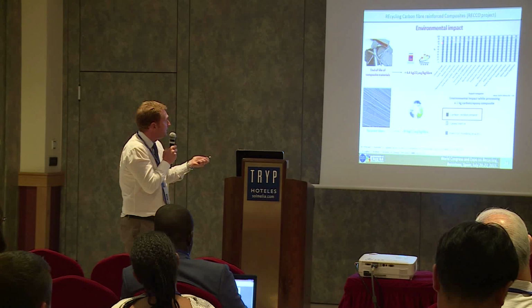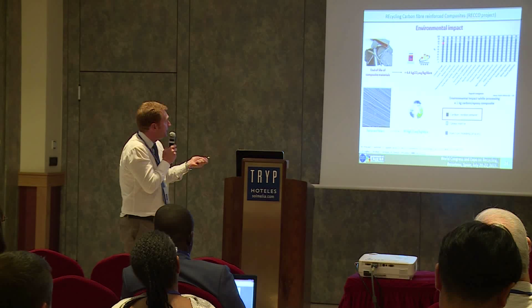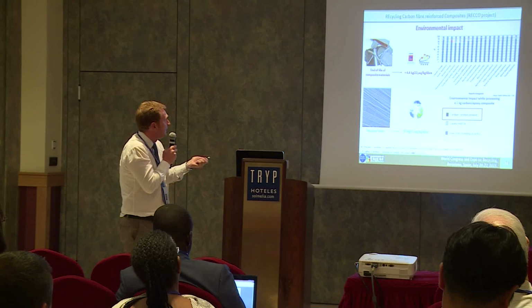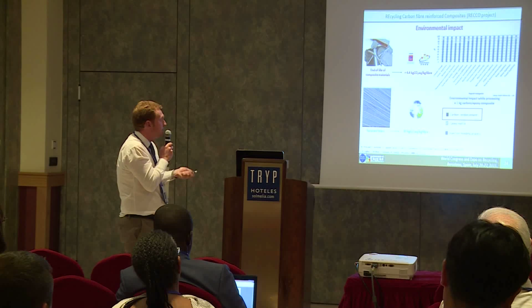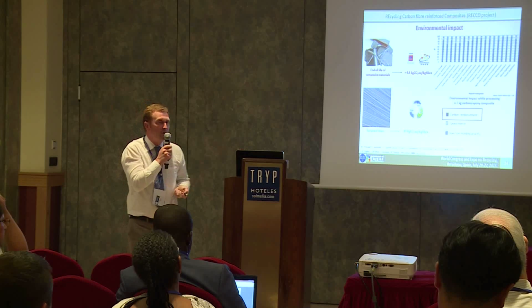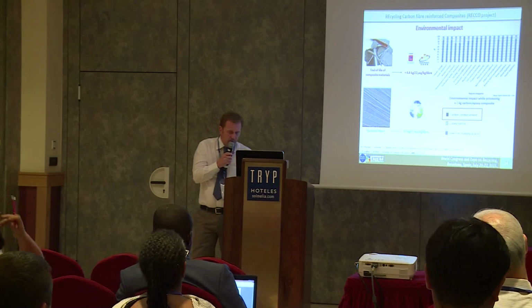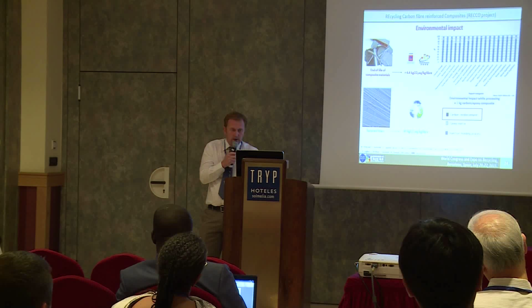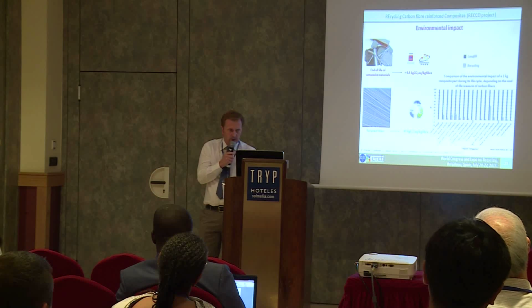And you see here on the histogram the impact of the different material contributions. So in black, the fiber, the most important, and after that the epoxy matrix and the injection process. So this is really a proof that there is a real need to recover this kind of material.